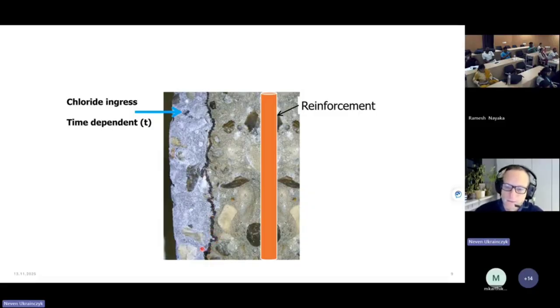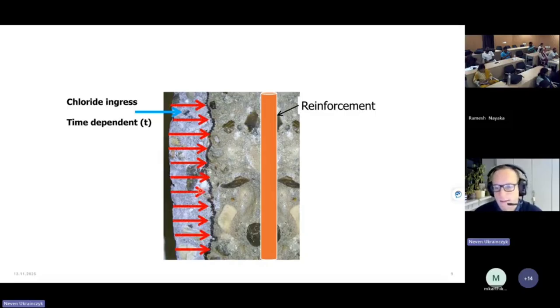And this becomes very important, for example, if you have low water-cement ratios and also slag, because then the microstructure is very dense, and then the ITZ, the porous zones, starts to be the critical path that the chlorides follow.